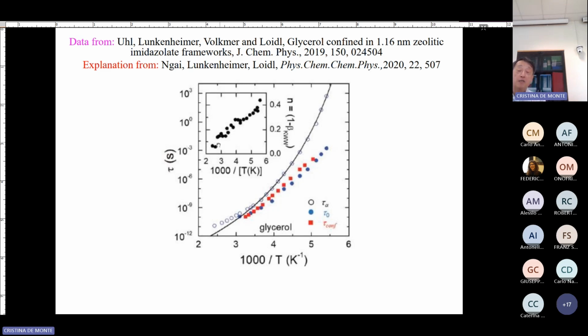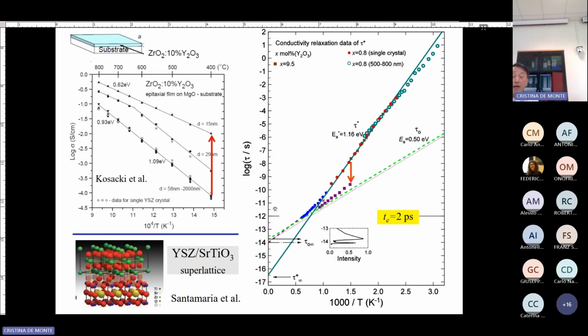You see, this is experimental for the bulk. So this is the bulk tau alpha. Okay, you can calculate that. So tau zero is calculated with the blue one, and the experimental confined value, a red square, is right there again. So even with very different materials, the same thing. So I just conclude with an entirely different material.